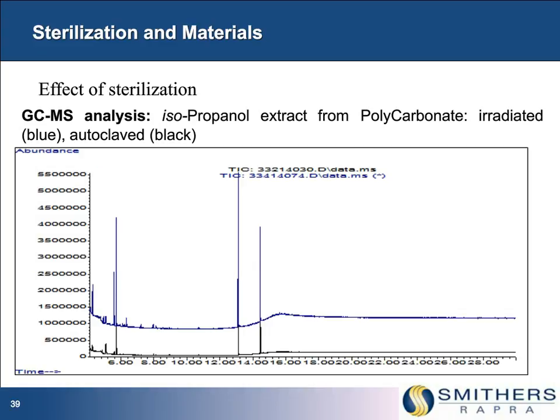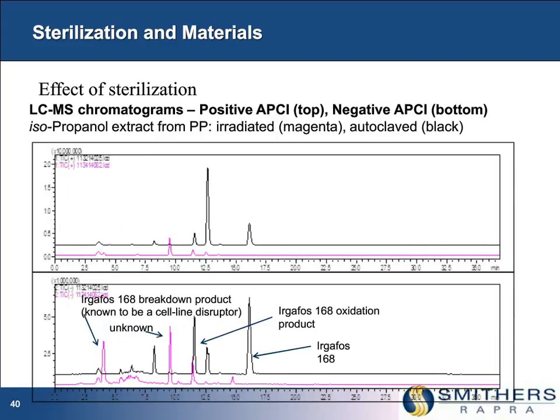And the final example, we're doing LCMS analysis, so we're looking for the semi-volatile to non-volatile species. And this time we're seeing a different distribution in terms of what chemical species are seen between the irradiated and the autoclaved. And all the Irgafos 168 chemicals are antioxidants. So the antioxidant is actually breaking down, and depending on the route of sterilization, in different ways. And you may think, well, why should I add an antioxidant?